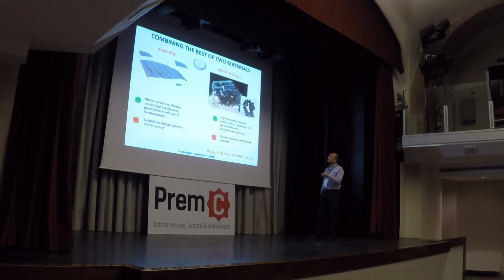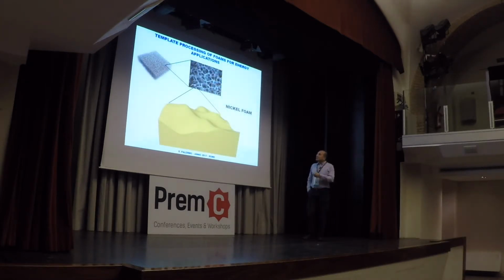The goal is not to find the best way to use graphene, but to find ways to combine it with the best material. People are trying to combine it with sulfur, silicon. We used to combine it with this iron oxide called hematite, and this is much better than graphene for ion storage, but of course it's an oxide, it's not really conductive, the mechanical properties are not very good. So this is an example of how you can use the flexibility of the sheets that I mentioned, and the high processability of our electrochemically exfoliated graphene oxide to create nice structures.